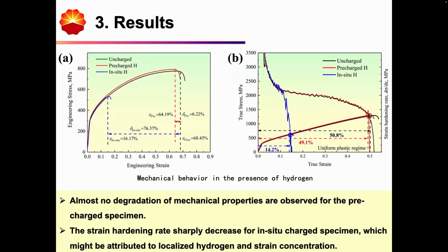Then we did some slow strain rate tensile tests. For the pre-charged compared with the uncharged specimen, almost no degradation of the mechanical properties is observed. Regarding the strain hardening rate, due to continuous TRIP effects, it offers a steady and stable strain hardening rate plateau during the test.